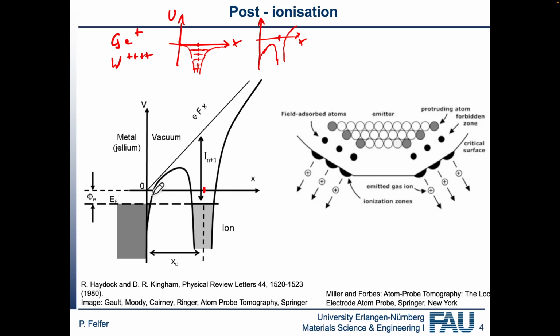And here what we have is not something going towards 0, but essentially an energy barrier like I've sketched here. So we've got a little energy barrier. So this is our energy barrier. And the energy barrier is obviously finite. And even if it was infinite, electrons can still tunnel, because the wave function goes out. And so essentially what can happen is that we get electrons tunneling through here. And this can produce higher charge states.